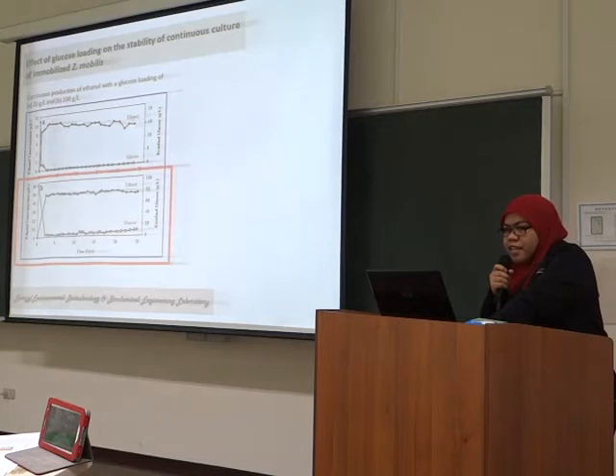And in here, you can see the most stable one is the 100 gram per liter of glucose loading. You can see for 20 gram per liter of glucose loading, the trend should be decreased for every 5 days, I think, and it's not stable for more than one month. But in here, after 20 days, you can see the ethanol production should be decreased, but it's not very significant, I think. So this is the conclusion.